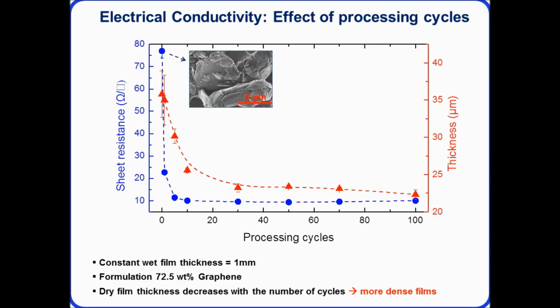So here you can see a typical coating with the unprocessed material. It looks like rocks, as we saw before. And then for the 100 processed cycles, we have a very flat planar film with quite low roughness.